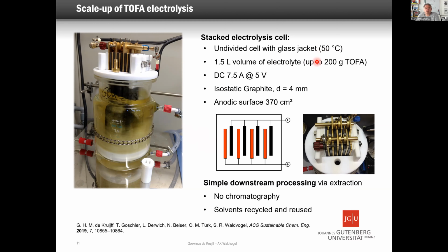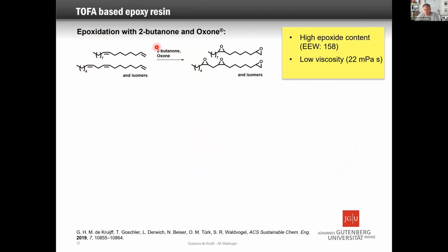And we work with about 200 grams of TOFA in there. You see, we need DC 7.5 ampere at 5 volts. And this works relatively nicely. And the good thing is the solvent can be directly recycled and reused. And there's no need for chromatography because the electrolysis is almost clean and smoothly made. Then you use that to make the epoxidation, for which some standard protocols were used here. And the important thing is that you have extremely low viscosity, which is unusual.